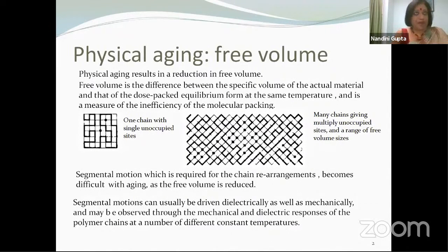It becomes more constrained, it becomes a more crowded space, and therefore in polymers, remember polymers have very long chains, and our dielectricity is governed by the movement of these chains. As the free volume reduces, the segmental motion of these chains becomes more constrained. The chains cannot rearrange themselves very easily, and with aging, therefore, the free volume is reduced and segmental motion is reduced. Why do we care about this? Because as I said, the dielectric properties of insulating materials are largely dependent on the arrangements and the motions of these polymeric chains.